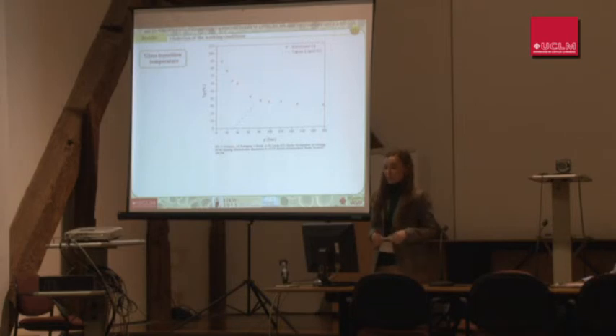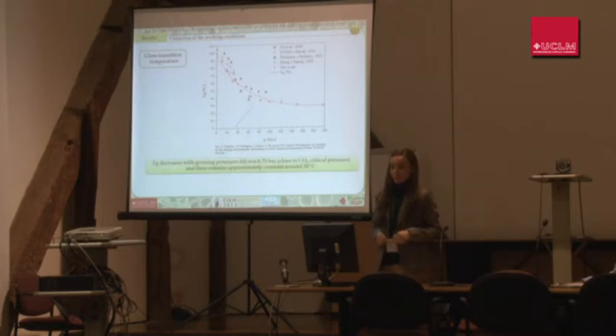As we can observe in the graph, when carbon dioxide pressure increases, the Tg decreases. But when we are close to 70 bar, the Tg is kept constant, and this is because the saturation is finished. We decided to compare our data with other data from the literature in order to check its reliability, and as we can observe in the presentation, they agree pretty well.